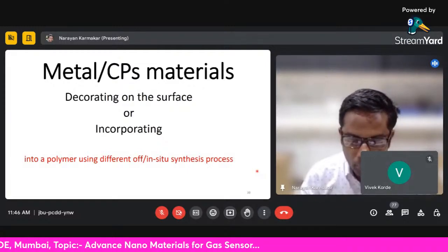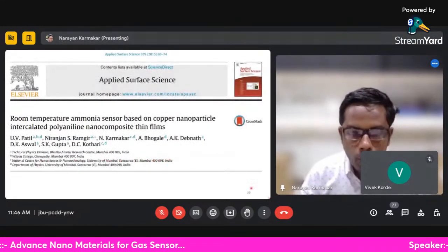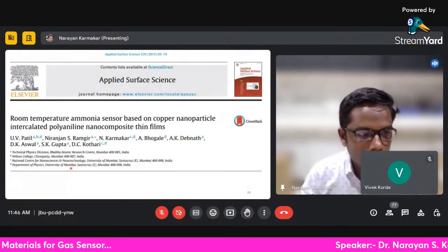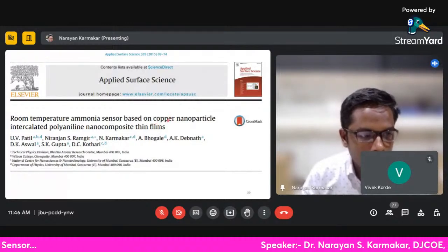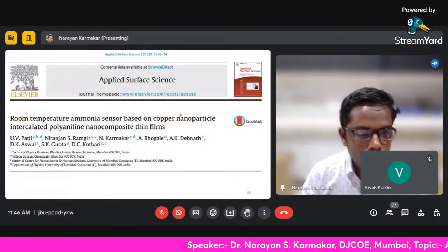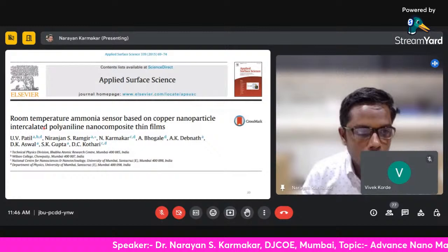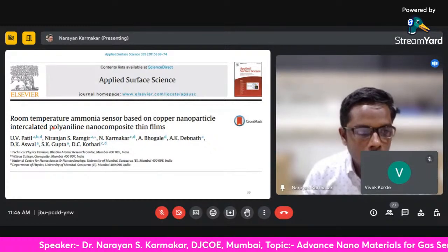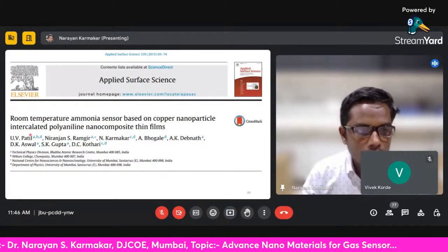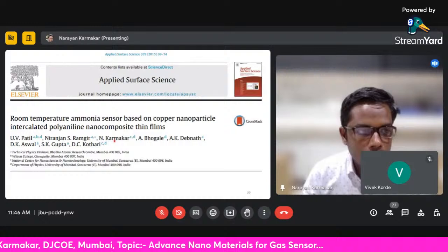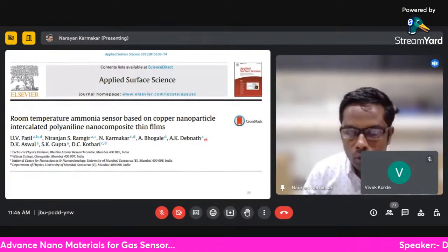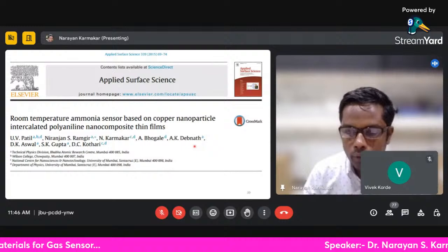As the first example, we make use of copper nanoparticles, and we have made a nanocomposite of copper nanoparticle with polyaniline. We see that this nanocomposite can detect ammonia gases up to ppm level at room temperature. So why copper nanoparticle?